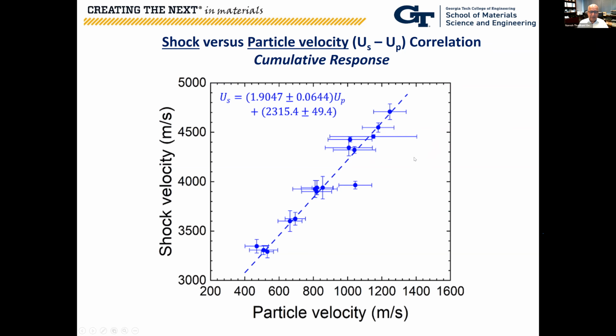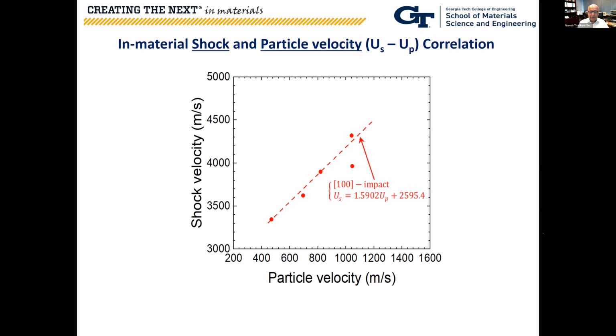But what about the orientation effect? Remember, we did impact experiments along different print orientations. So if I were to look at that individually, these are the data points for the experiments performed with impact along the 100, that's the print direction. You can see the data points. The error bars are not indicated here because they were huge, and I think they mess up the overall plot. But you can see the overall trend with the limited number of data points that we have for this orientation.